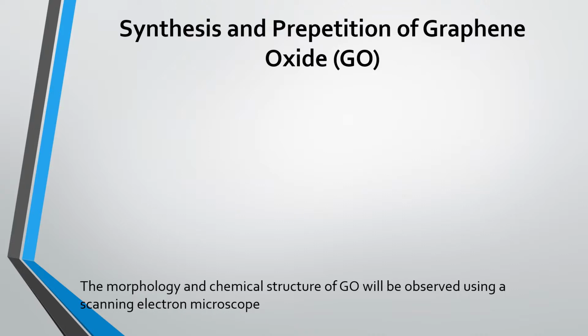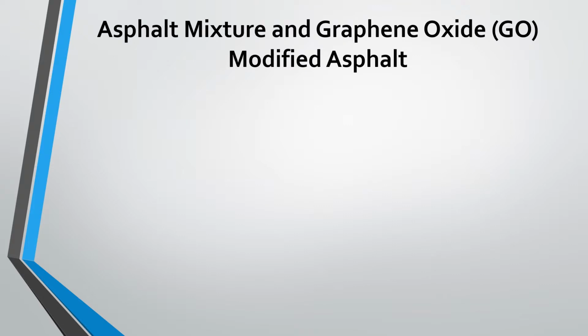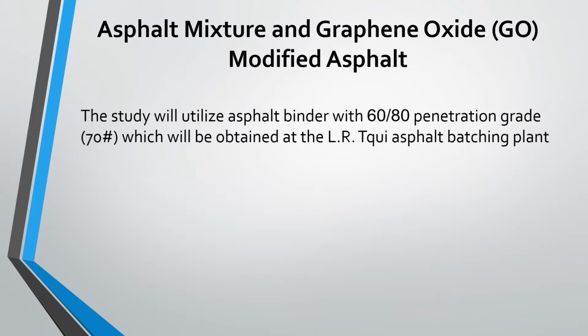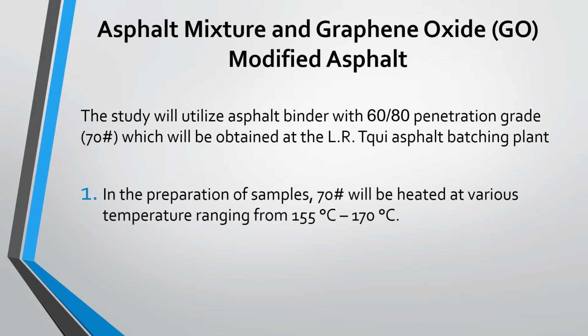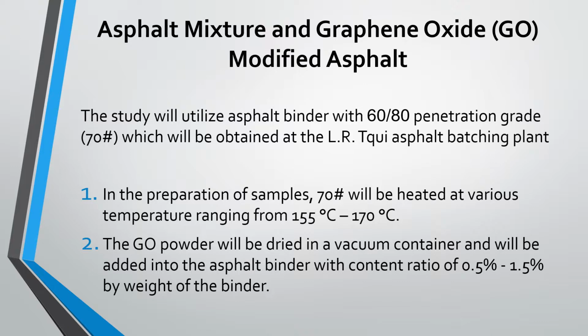The study will utilize asphalt binder with a 60 to 80 penetration grade, which will be obtained at the L.R. Tqui Asphalt Batching Plant in Bulacan. In the preparation of samples, Asphalt 70 will be heated at various temperatures ranging from 155 to 170 degrees Celsius. The GO powder will be dried in a vacuum container and added to the asphalt binder with a content ratio of 0.5% to 1.5% by weight of the binder.